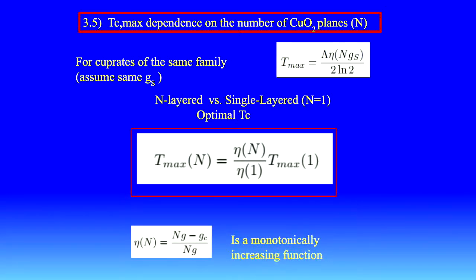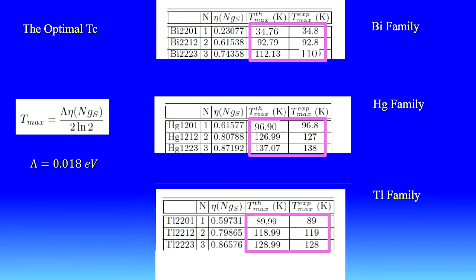Now, the dependence of temperature on the number of planes. I take this expression for T maximum and consider a single family, namely bismuth or thallium or mercury, and assume that GS, that coupling, is the same for all members of the family. Then the maximal temperature for each family is given by this ratio. So if I go there, I see T maximum, my theoretical value and the experimental value.